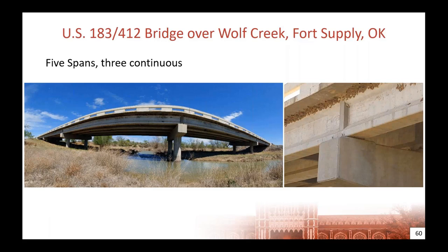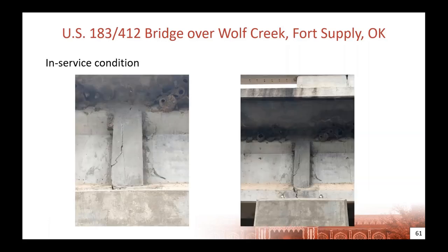There's the panoramic again, and then a picture of the linkage block continuity joint that was used on that bridge. And then this is the picture of the damage that was caused in that continuity joint. This is the exterior joint. As you can see, it's got pretty extensive large cracking that occurred, and it extends all the way to the bottom, which indicates the positive moment issue caused by the creep and shrinkage issues.